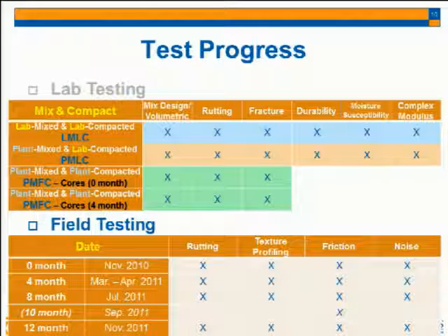And also we did the full field testing right after construction, and also every 4 months after construction, up to 1 year. So that's why we have the 0 months, 4 months, 8 months, and 12 months. After 1 year, we do the same test every year. So the next field testing for 24 months will be next month, actually.